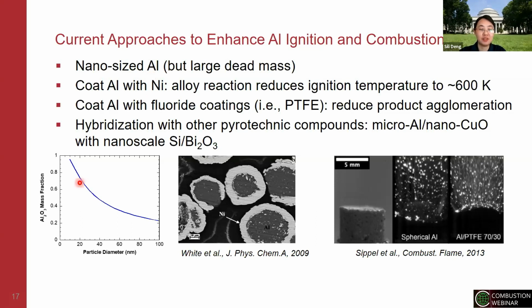As you can see from this figure, when the diameter of the particles shrinks to 20-ish, almost 80% would become aluminum oxide, and they cannot be burned anymore. So yes, we might see the reactivity enhanced by using nano-sized aluminum, but the total available aluminum would be reduced when the size shrinks.